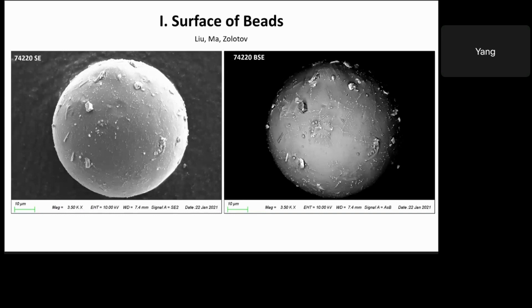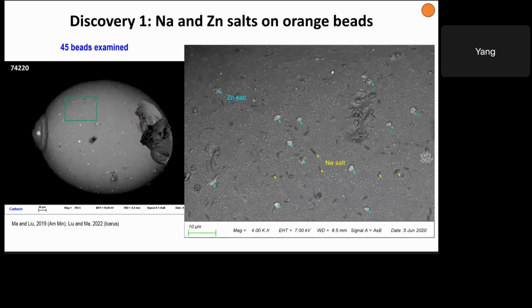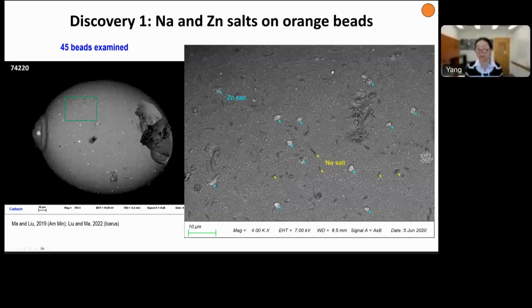Okay, so the first discovery we encountered is for orange beads. In the upper right corner, I put a circle to indicate what type of glass beads we found the features in. It was a bit surprising when we were observing the orange beads. We see that the surface contains two types of salts or phases.